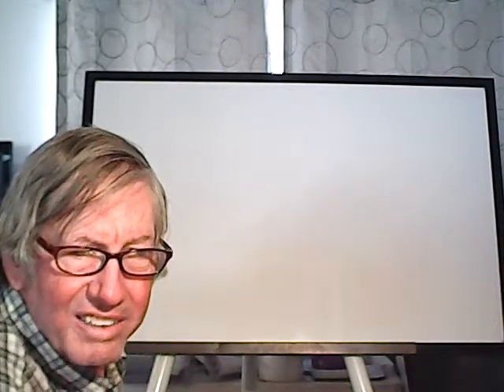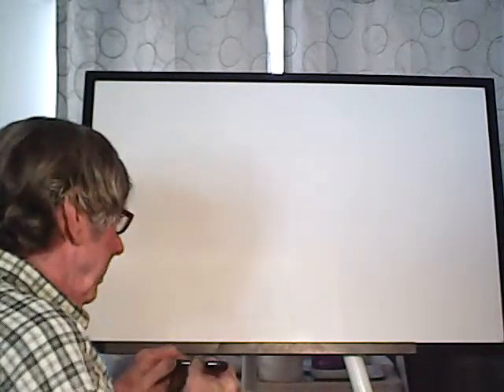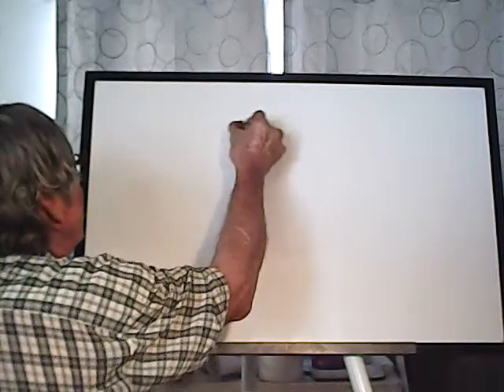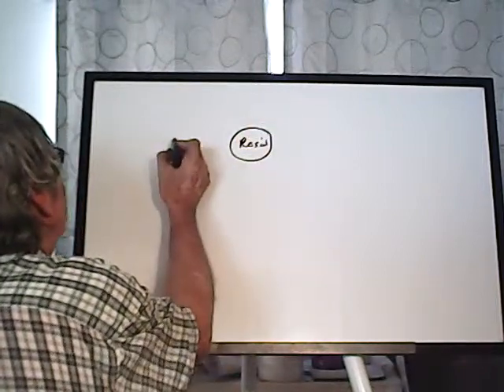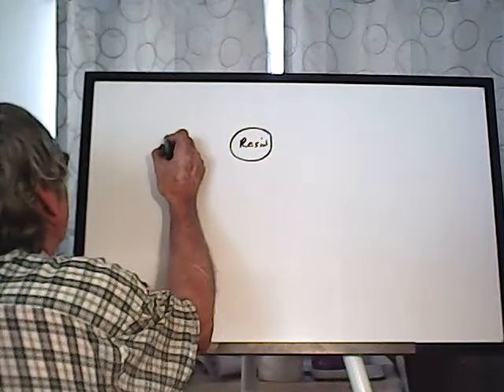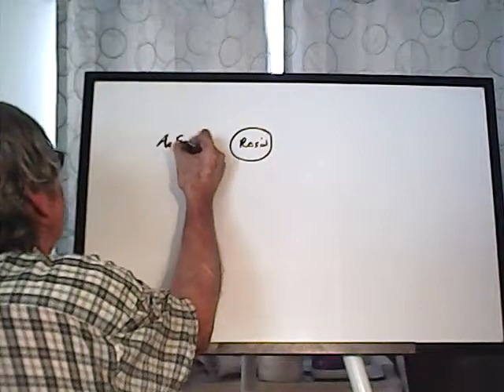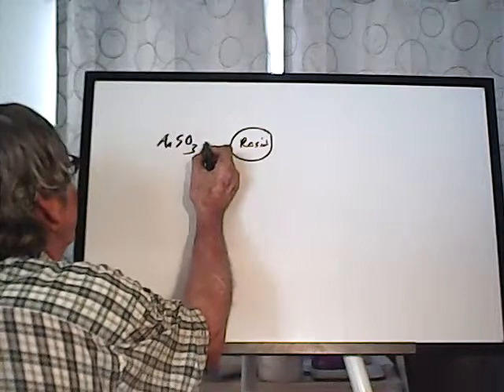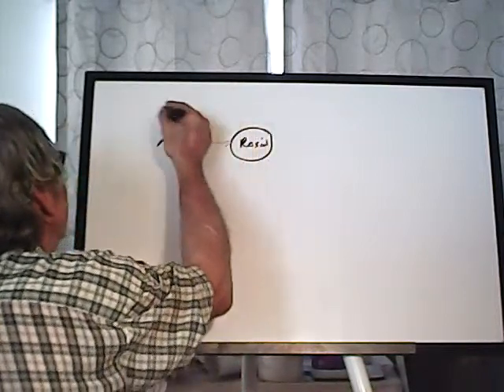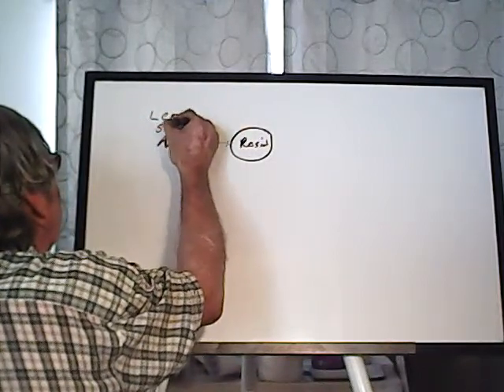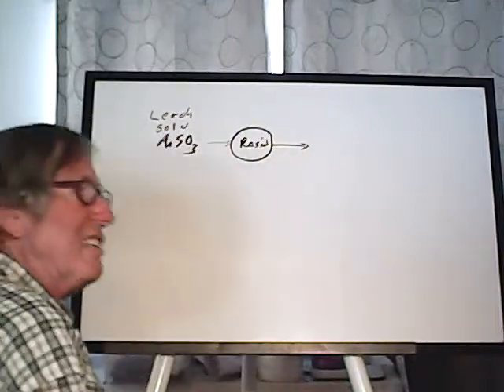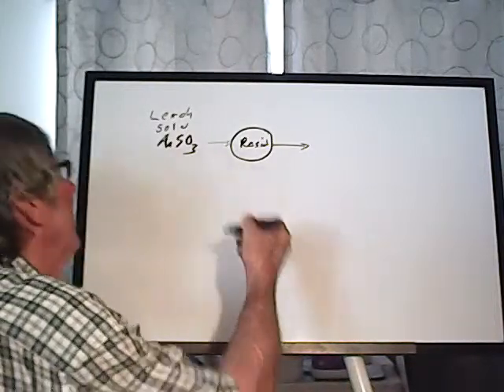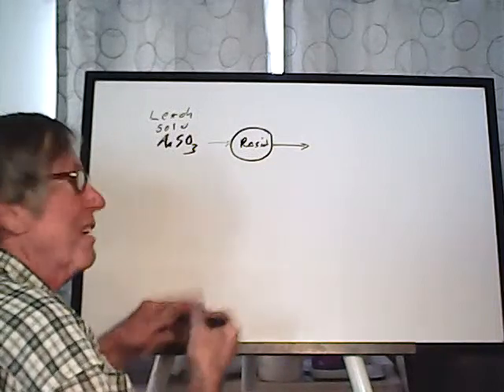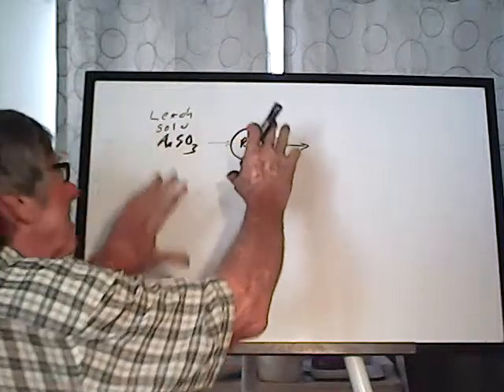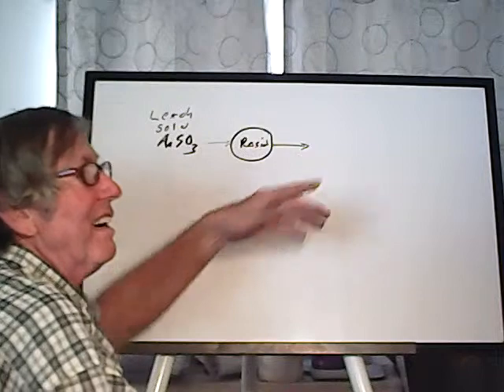So when you have a resin bead and you have a gold thiosulfate ion that wants to stick to it under the leaching solution, then to get it off of there, you have to change the conditions. You may heat it, raise the temperature. You may change the chemistry. The theoretical chemists and the practical chemists figure out what you do to the conditions to cause this reaction to go the other way. And that's called stripping.